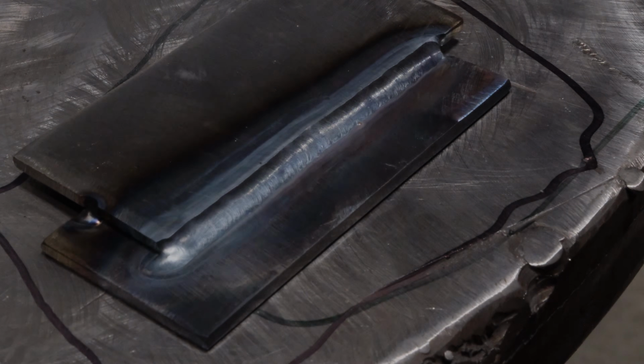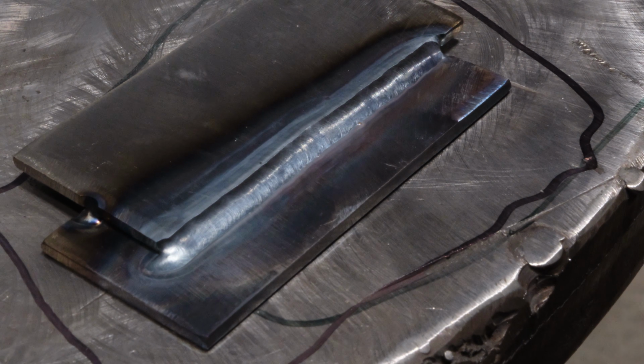We're going to look at a different angle of approach with a little bit better detail, a little bit better clarity shortly. But everything is going well here, very consistent arc gap, consistent travel speed. This is what you want. Realistically, I could have used more amperage, but it worked. So now let's look at what that looks like when we're done. So not the best looking fusion weld, but it will definitely hold. Again, 1/8 inch isn't something you really want to be doing fusion welds on. Generally, it should be reserved for a lot thinner material, but it did weld it and it'll work.